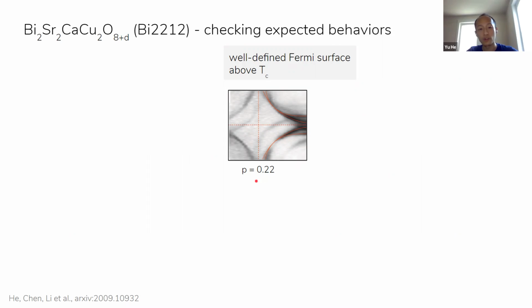First of all, we can perform photoemission measurements of the entire Fermi surface, and this is one of the aspects that Chimiao asked about a little bit earlier. We see that at 22% hole doping, there is a coherent continuous Fermi surface extending all the way from Brillouin zone boundary to Brillouin zone boundary. In comparison, if we look at 18% doped Bi2212, near the antinodal region it's a blob of intensity, which we now know as a pseudogap, that doesn't have any sharp quasiparticles or clear dispersion.